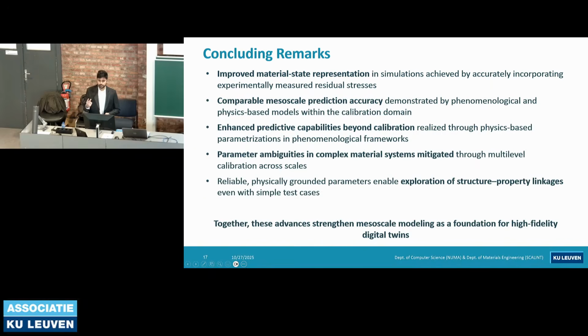In that case, we used two different RVEs. One was a bicrystal, which corresponded to the ideal scenario of having two microtexture regions right next to each other, and this was infinite because it's an RVE. Then, to add complexity, because we also saw that at other regions there were not only lamellae but also other intermediate orientations involved, we increased the complexity by having a random polycrystal. So this is not the end. We can again increase the complexity and make it more representative of the actual state. Okay, thank you.